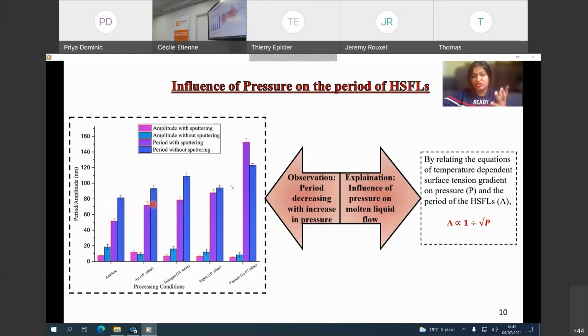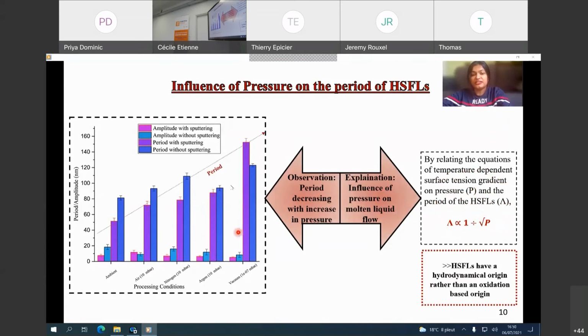And as we made the pressure smaller, at 10 millibar pressure, the period increases a little bit, and at very small pressure, that is at 10⁻⁷ millibar pressures, the period is very high. So as the pressure decreases, the period increases. And this observation could be explained by the influence of pressure on molten liquid flow. By relating the equations of temperature-dependent surface tension gradient on pressure P and the period of HSFS, we were ultimately able to derive an equation which stated that the period of the HSFS varies inversely to the square root of the pressure. And this observation concludes that the HSFS have a hydrodynamical origin rather than an oxidation-based origin.